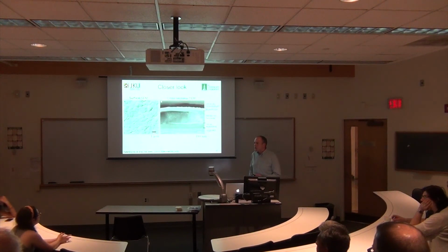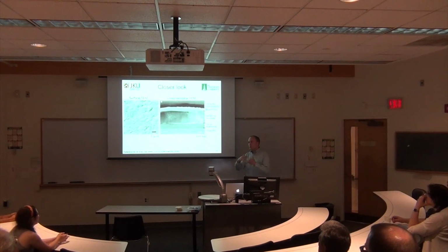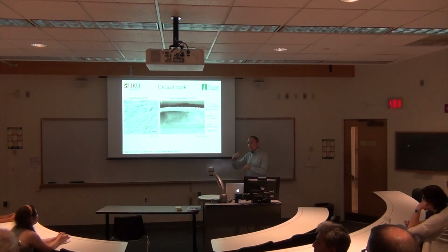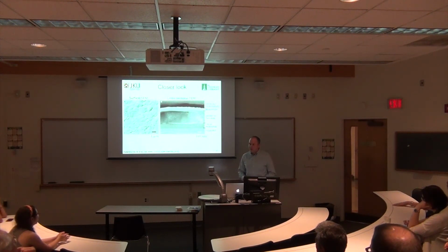So you can make layered structures without much more cost? Presumably, but the problem with making layers is the same as with any sequential layer processing—it assumes your bottom layer is perfectly flat and indestructible by the techniques used to deposit the second layer. If the lower layer is soluble and you put a solvent on top, it will dissolve the first layer unless it's protected. So the process engineering has to be very specific: put down something, protect it, then put down the second layer, and the protecting layer can't interfere with the device. Does that make sense? It's not easy, but it can be done.